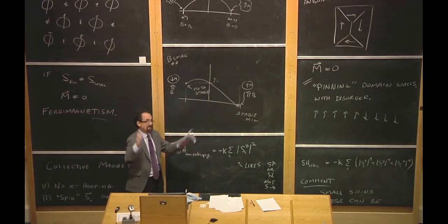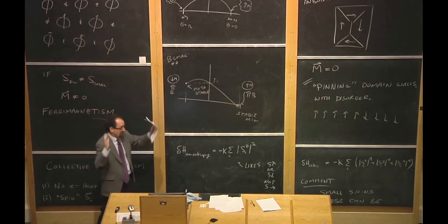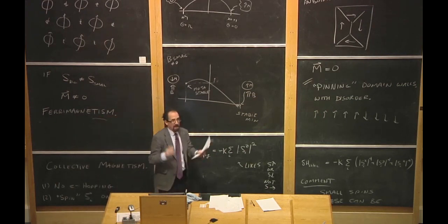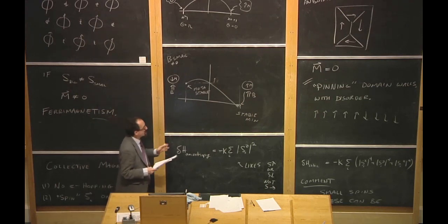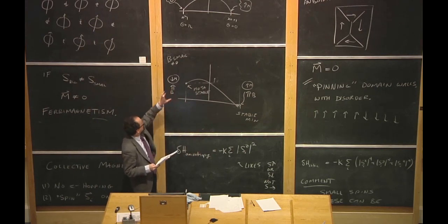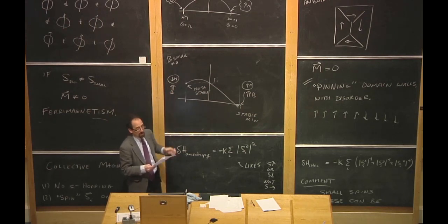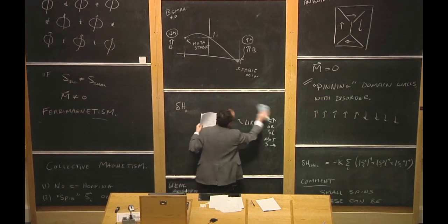And this means you have to take all of your atoms, maybe a million of these atoms, and somehow flip them all over simultaneously, either thermally or by a quantum tunneling. And that's a process that's so difficult that at low temperature it may never happen. So you can have these little crystals of magnet have their magnetization stuck in the wrong direction. Now let's turn up the magnetic field a little bit more.